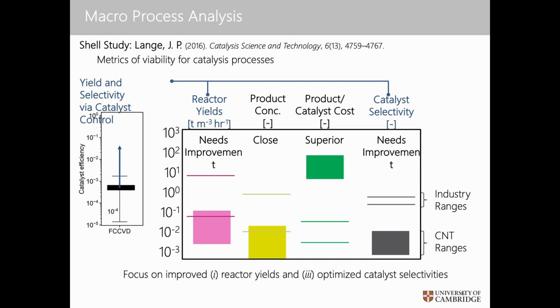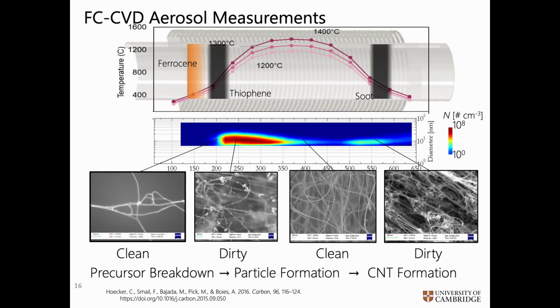And to highlight that, less than 1% of our catalysts actually grow these materials. And so understanding that and why those catalysts aren't being used at as high a rate as possible, or a high fraction as possible, is where we really could gain orders of magnitude improvement, and then that would directly improve our reactor yield. So that's where most of the academic interest is in this, and motivated by this industrial need.